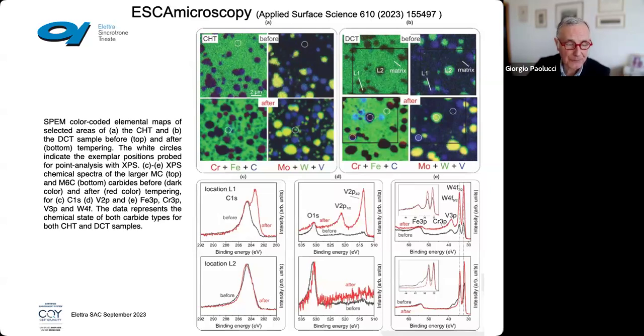If you look at the first image in the top left of this slide, that bar is 2 microns, so the resolution is of the order of 100 nanometers, but you can do even better than that.